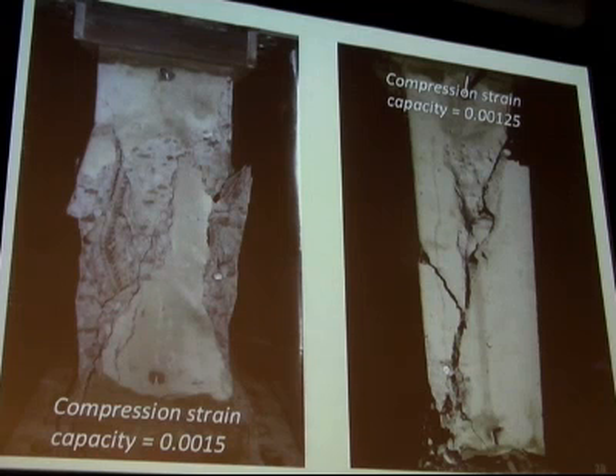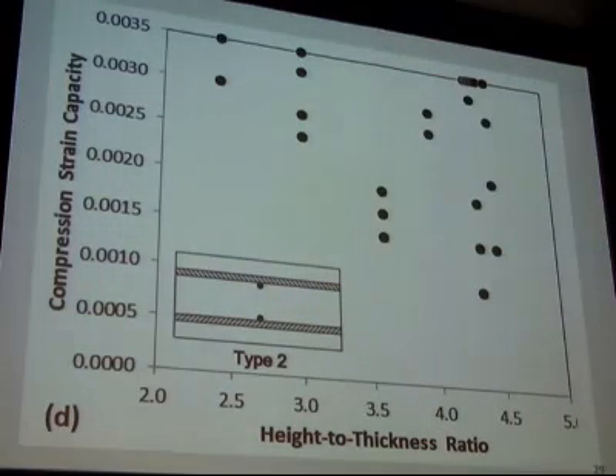And I guess I have a pointer, but I'll use this one. So if you look here, here's a horizontal bar, okay, vertical bars there, and there's another horizontal bar, and there's a failure crack connecting these reinforcing bars. And that's very typical of what we see. When you've got a narrow element under high compression, we get this complete failure plane going right through the element. And there's just a summary of the tests we've done now over a few years. If you look here on the compression strain capacities, as low as less than 1 part per thousand when the elements get more slender.